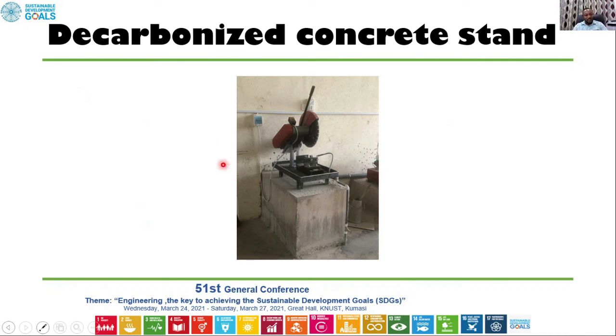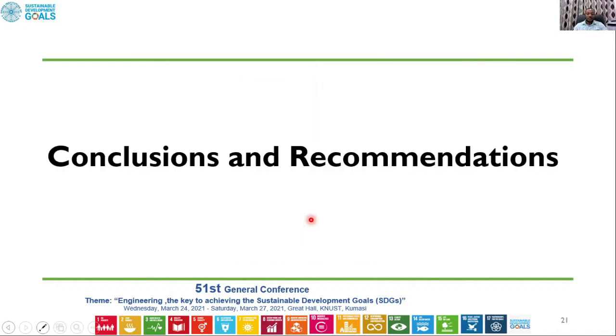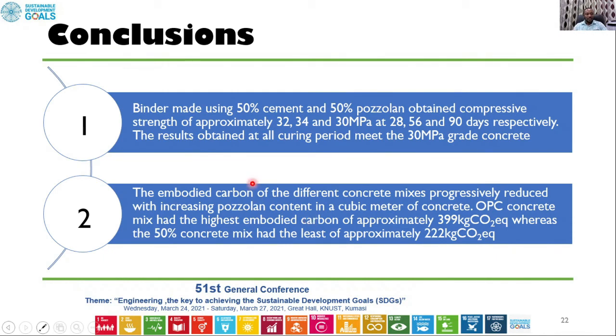So after all these things were done, we tried to practicalize the mix. So we mounted this cutter, a concrete cutter, on this stand, and this stand was a concrete mix containing 50% pozzolan and 50% cement, and it was a C30 concrete. So these are the conclusions I made from this study.